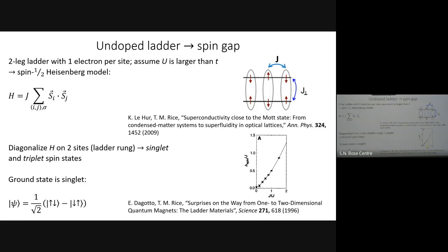There are some very famous papers. This paper has thousands of citations, with Dagotto and T. M. Rice. What they're doing, I will move out. This J perpendicular, J prime, is this one. It doesn't matter how small this is. The delta spin is non-zero. It goes to zero this way. For the smallest J prime, there is a spin gap. Why is there a spin gap? Because the singlet has to go to a triplet. There is always a gap. So this paper is quite famous. If you do this, you are always going to get a singlet.